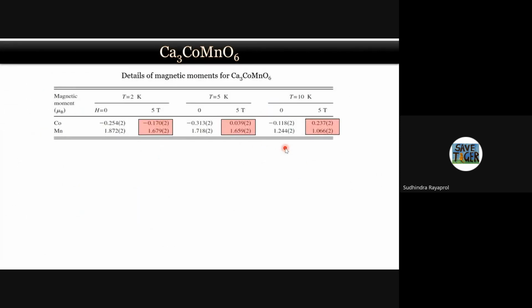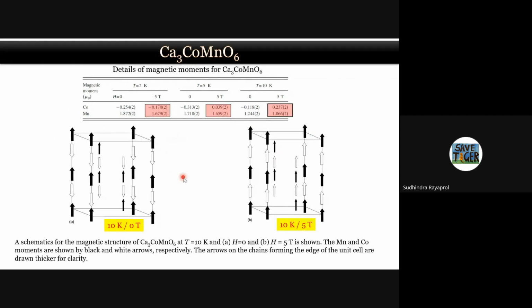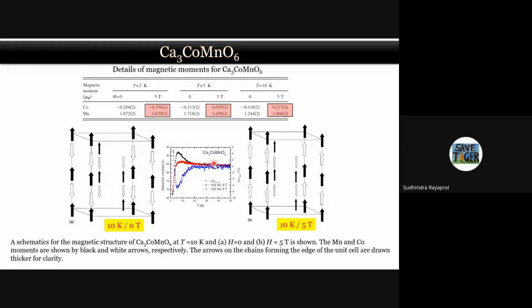If you look at the magnetic structure and the magnetic moments which you get from it, it shows that in zero field at 10 Kelvin, we have this antiferromagnetic structure between cobalt and manganese. Cobalt is ferromagnetic and manganese is antiferromagnetic, but the cobalt-manganese interaction is antiferromagnetic. But the moment you apply a 5 Tesla field, you turn all the cobalt moments to the positive side, you make them align along the c axis, and you have a net ferromagnetic moment. So you have field induced changes, which we saw in magnetization also, and in the magnetodielectric effect also. So this shows that when you apply magnetic field, there is a change of cobalt moments from antiferromagnetic to ferromagnetic order.